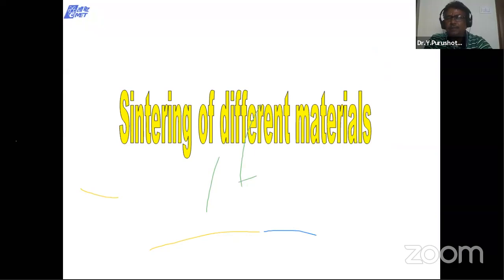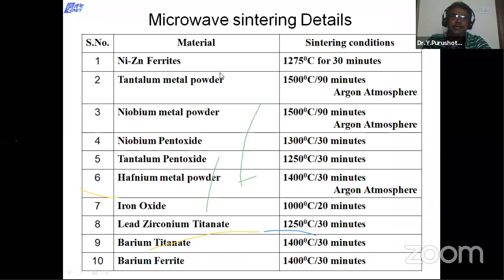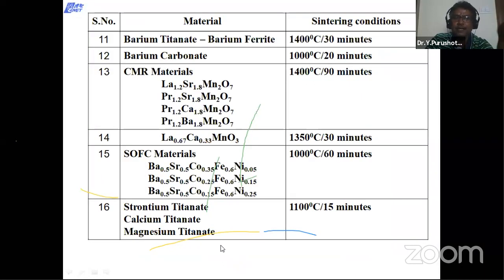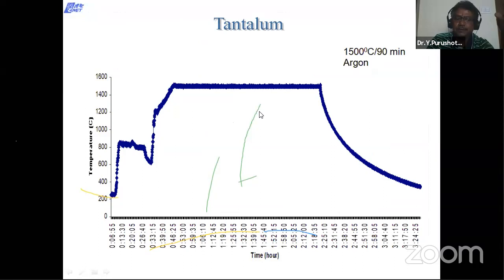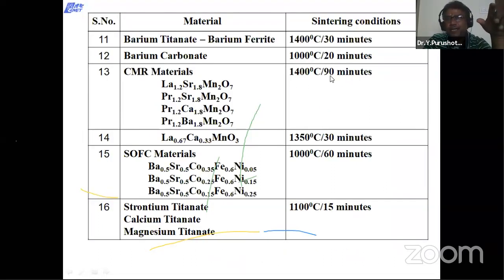And after establishment of this microwave furnace, we sintered a variety of materials. Not only refractory metal powders, but nickel zinc ferrites, tantalum metal powder, niobium metal powder, oxide materials, hafnium metal powder, iron oxide, PZT, barium titanate, barium ferrite. From our Osmania University and even others, many people utilized it with different sintering conditions. Many materials, and it is still going on.